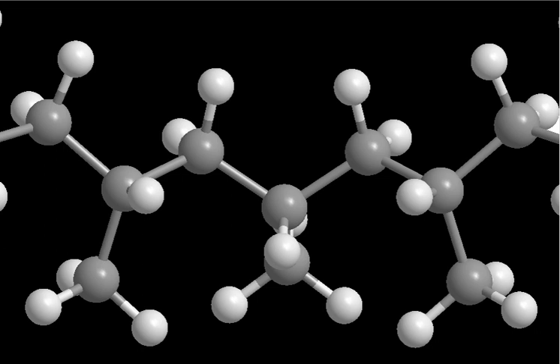Commercial isotactic PP has a melting point that ranges from 160 to 166 degrees Celsius, 320 to 331 degrees Fahrenheit, depending on atactic material and crystallinity. Syndiotactic PP with a crystallinity of 30% has a melting point of 130 degrees Celsius, 266 degrees Fahrenheit. Below 0 degrees Celsius, PP becomes brittle. The thermal expansion of polypropylene is very large, but somewhat less than that of polyethylene.